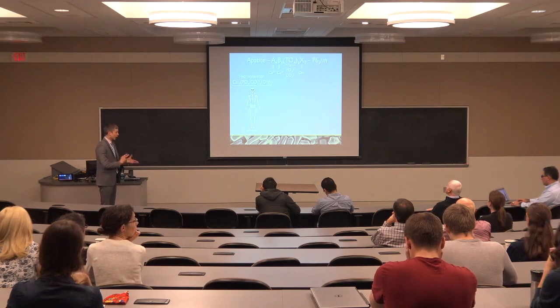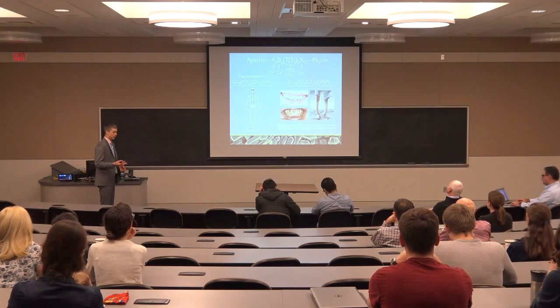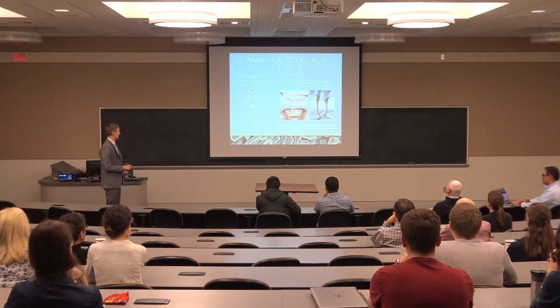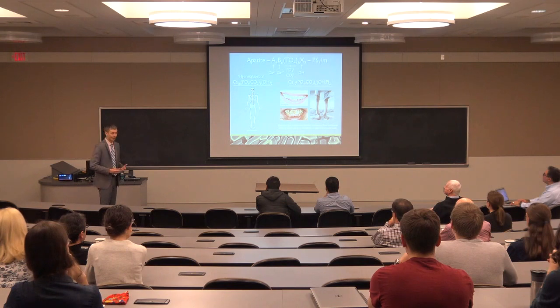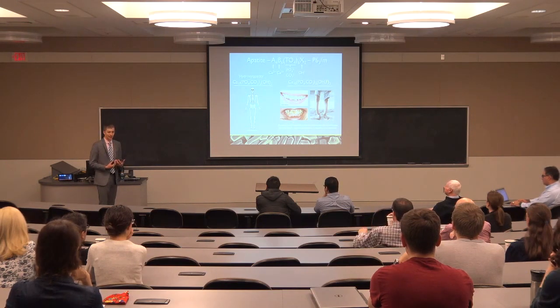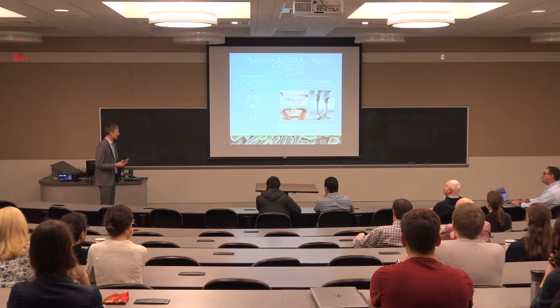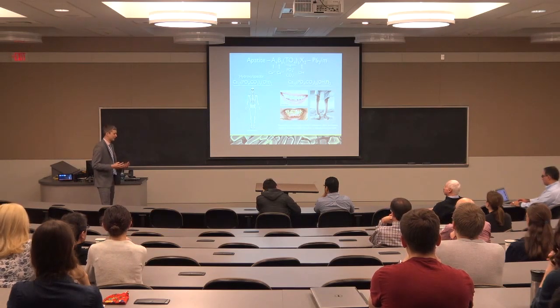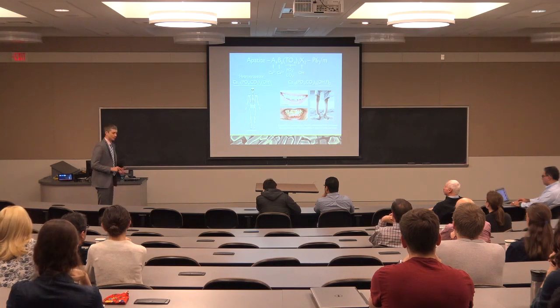And we can change slightly the makeup of this. So if we consume fluorine in our diets and our drinking water, a little bit of fluorine substitutes for some of the OHs and improves the acid resistance, improves the quality of our teeth. A nice, bright smile without cavities. The problem is that when we take in too much fluoride, the chemistry changes, and instead of improving the properties of the teeth, it can lead to pretty significant dental and skeletal issues. So there's a balance here.